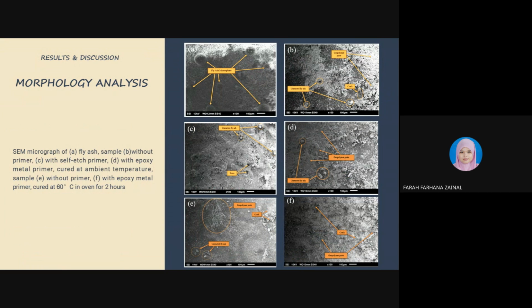So from the figure, the microstructure analysis of the geopolymer coatings on mild steel pipeline as observed in the SEM micrograph provides valuable insights into their characteristics. So similarly, the sample with epoxy metal primer also exhibits a combination of unreacted fly ash and geopolymer paste, indicating a more cohesive structure compared to the sample without primer. As we can see, for B, for C, for D, for E, there are unreacted fly ash in these SEM results.